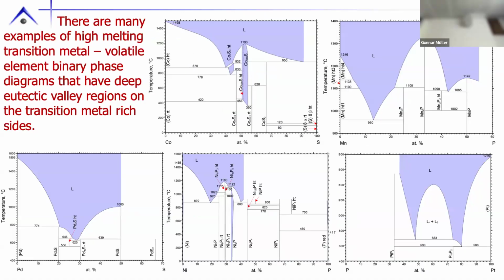Also, yes, very nice question. Actually, the phase diagram you just showed, well, doesn't matter which one. If I wanted to vary the composition, I start from the liquidus and I just choose a different percentage of the initial material. Right. So if I wanted to grow palladium for some reason, I would put 10% sulfur, 90% palladium. If I want to grow this, I basically start with a single phase liquid. This line here is defined by what I put in the crucible. Okay, so if I want to go over here, I put more sulfur in the crucible to start with. Absolutely. And we'll come back to that in a moment or two.